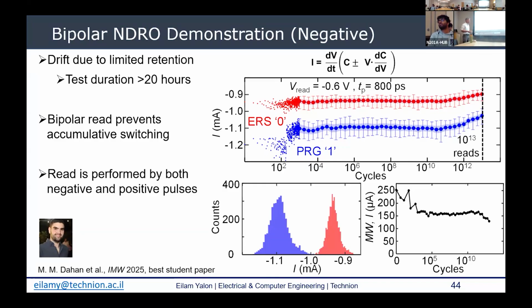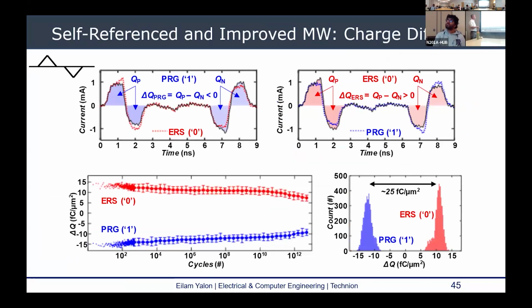But we can also read out the charge. And not only the charge, what we're doing is we apply two consecutive pulses, positive and negative, and integrate them. Because here there is a difference. We get this difference in the derivative directly from the difference between those two charges. So if it's in the program state, we'll get negative charge when we subtract one from the other, and in the erase, we'll get positive. And this is what you see here.